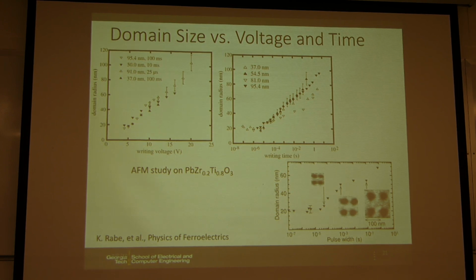Here I'm showing the domain size as a function of write voltage and write time. As you can see, the domain size is pretty linear with the writing voltage for different thicknesses of PZT samples.